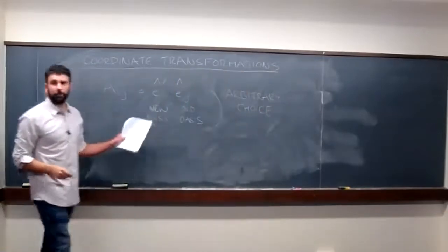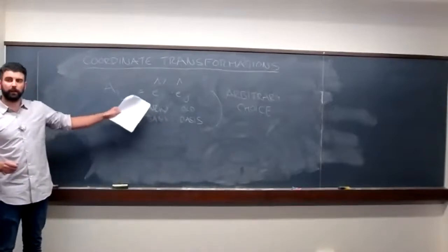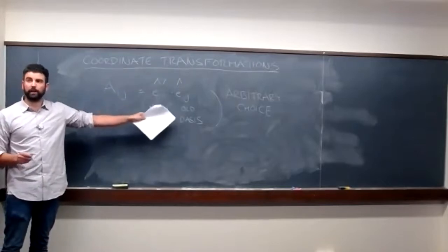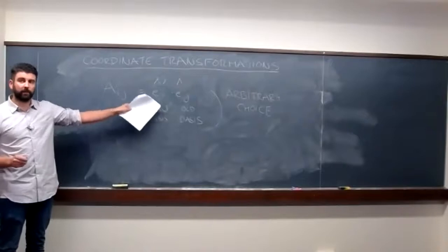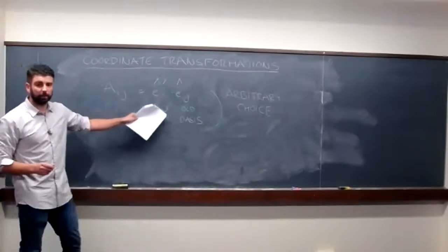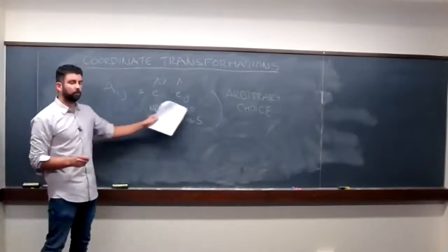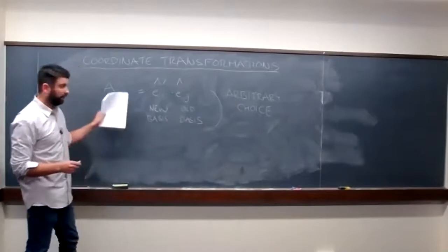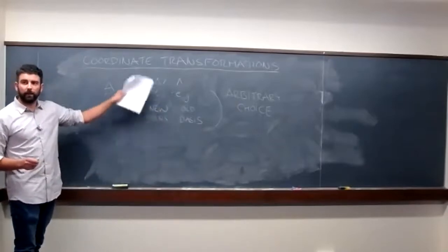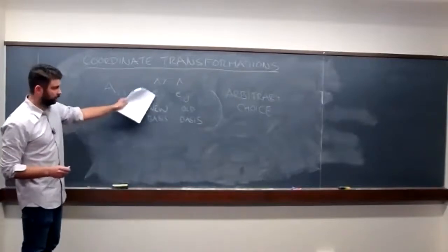So when someone gives you a data set that has a whole bunch of coordinate transformations in it, that says maybe what the collection of crystal orientations are, you have to make sure to ask the person giving it to you whether the convention they're using is new basis times old basis or old basis times new basis. In this class, we're going to use new basis times old basis. And this is going to be one of a couple of times in the class where I am going to point out something that can cause a big problem as you're processing data. So this is one right here.